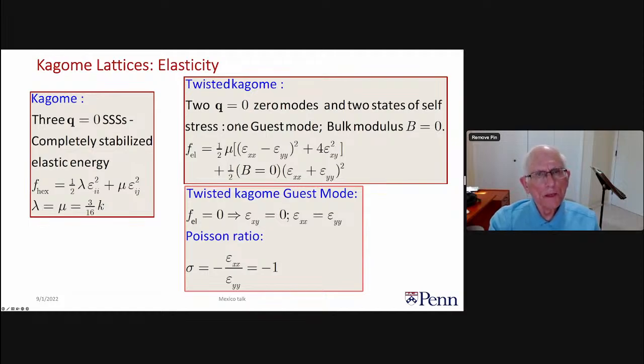When we go to the twisted lattice, we found we had this guest mode where you can compress things isotropically. So here, looking at this, you can clearly see that there are two zero modes in the elastic energy, one in which epsilon xx is equal to epsilon yy, and one in which epsilon xx equals epsilon yy and epsilon xy is equal to 0. You need all of those things to give us a zero mode, which is basically the guest mode.